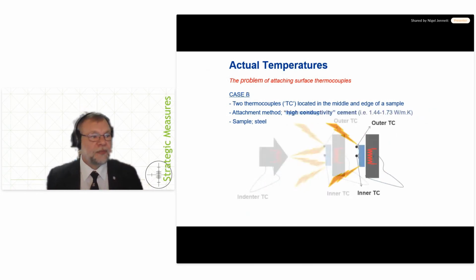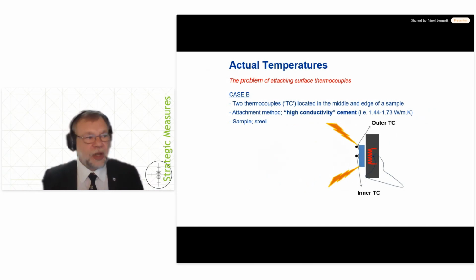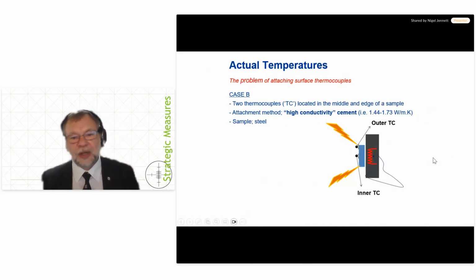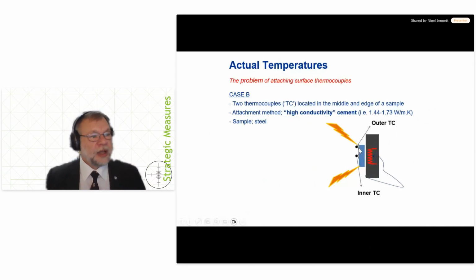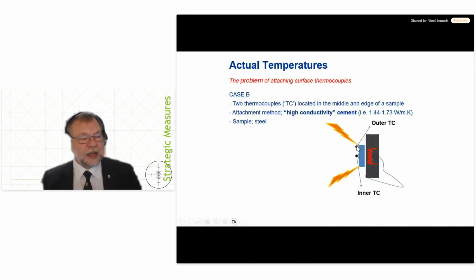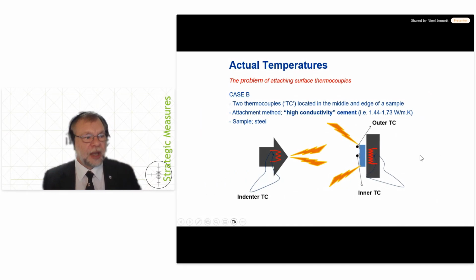If you put those thermocouples on using a glue, like a so-called high thermal conductivity cement, which is not really that high thermal conductivity compared to steel, for example, you can see that you're likely to get a thermal break here, which causes a temperature difference, and you do. So you do the same thing again, move it into the case.